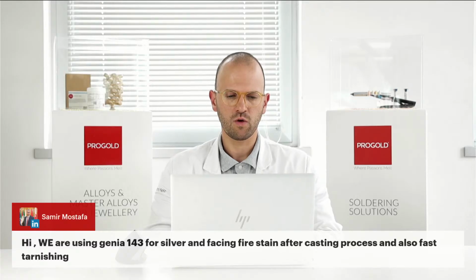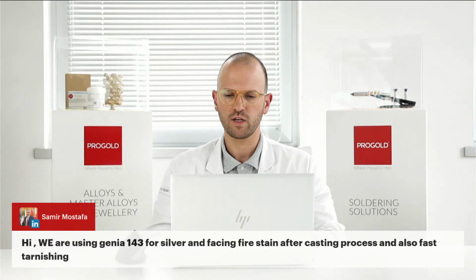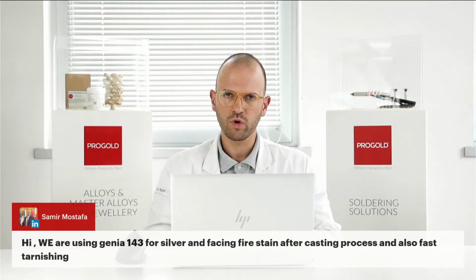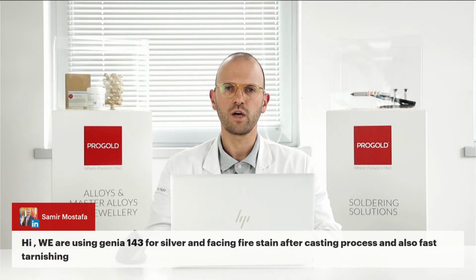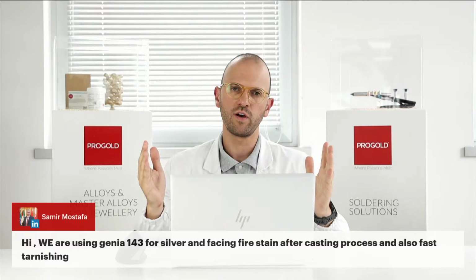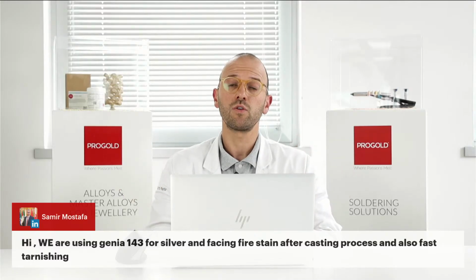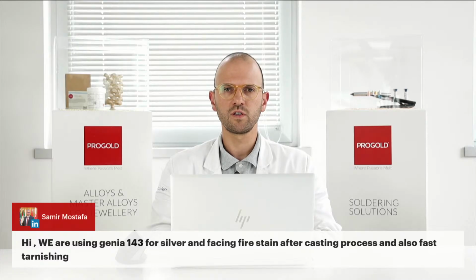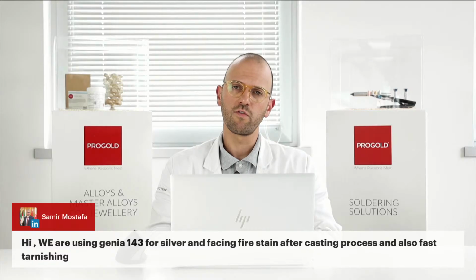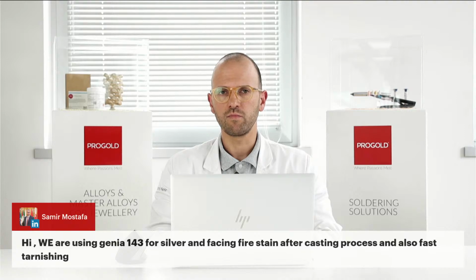We are using Genia 143 for silver and facing firestain after the casting process, and also fast tarnish. In this situation, it is advisable to lower as much as possible the time of exposure of the metal to a hot temperature. So the first suggestion is to cut the timing before quenching the flask during the solidification, and also try to reduce as much as possible the flask temperature and metal temperature.